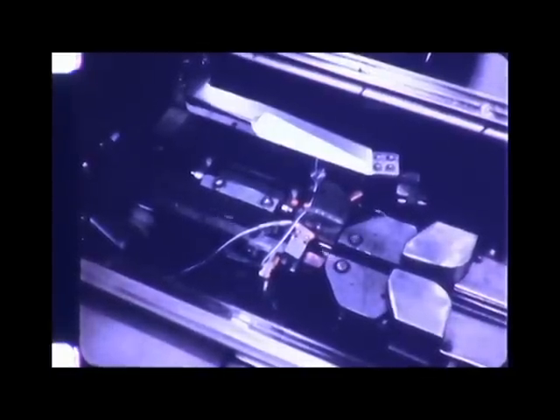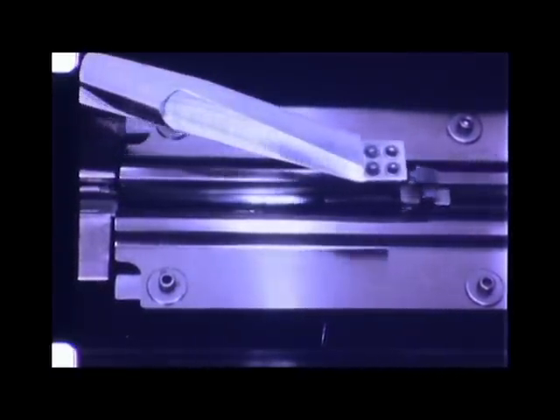The pellets are ground in a dry centerless grinder to diameter tolerance within 1.5 mils. They leave the grinder at a rate of about 3 pellets per second and proceed in a column to the laser inspection system. Here they're queued up to be pushed past lasers which scan them in batches of about 17. One laser measures diameter and length and checks chamfer dimensions, and the second one looks at the heat transfer surface itself to inspect for chips, cracks, and other imperfections.